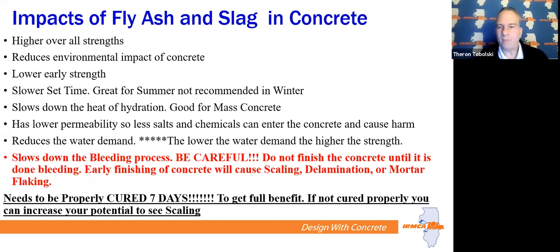The one thing we have to caution you about, we kind of talked about this a little bit, is when you use high replacements with fly ash or slag, it slows down the bleeding process, right? We need to be careful. When finishers are finishing concrete, they wait for the bleed water to come up, and then it dissipates and goes away, and then they do their finishing on the concrete. If they finish the concrete too early and they trap that bleed water in the concrete before it can dissipate, we see things like scaling, delamination, or mortar flaking, right? Those are all bad issues with concrete.